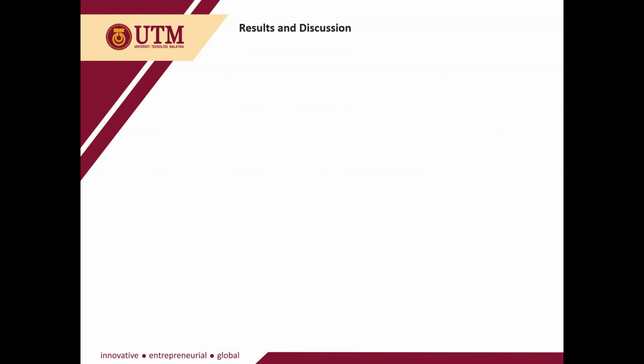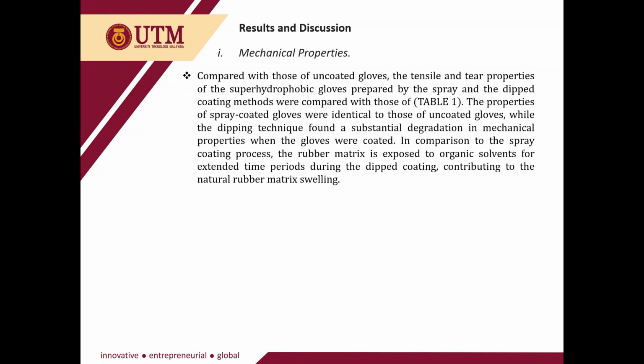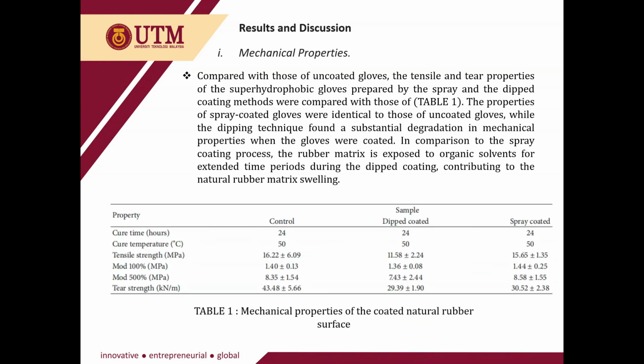Next, we move to the results and discussion. As for the mechanical properties, to compare with the uncoated glove, tensile and tear properties of the super hydrophobic gloves prepared by the spray and the dip coating methods were compared in table 1. The properties of spray-coated gloves were identical to the uncoated gloves, while the dipping technique showed a substantial degradation in mechanical properties when the gloves were coated.